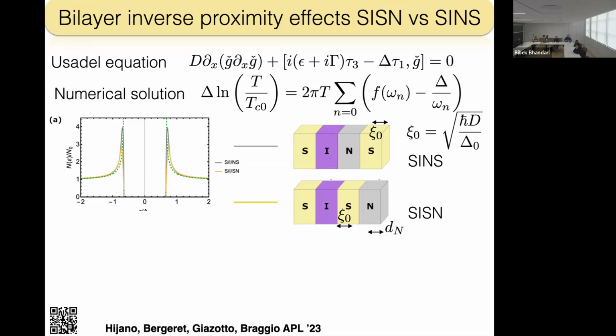the thermoelectric effect. The problem is not getting a good Seebeck coefficient. If you speak to the people that work on this, the real problem is to keep the temperature gradient sufficiently high. And in a certain sense, this explains why this effect is so strong in superconductors, because in this type of junction you create the highest gradient in the universe, 10 to the 9 Kelvin per meter, because the thickness of the insulating barrier is 2 nanometers.